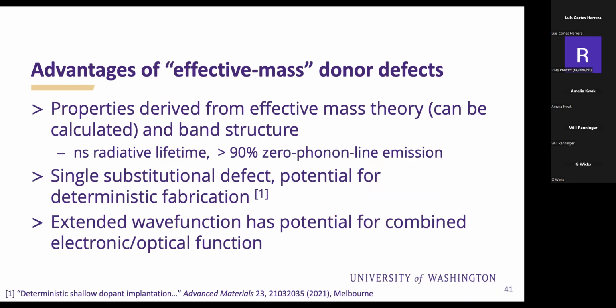Some advantages of effective mass donor defects are that the properties are derived from effective mass theory, which is a very well-established theory from band structure, or from Bloch's theorem, essentially. And then you have a single substitutional defect in this case, which gives you the potential for deterministic fabrication. Phosphorus in silicon gets 99.85% incorporation probability for putting in one phosphorus ion. That's pretty incredible in terms of yield. For a nitrogen vacancy center, you're jumping up and down if 10% of the nitrogens that you put in can yield an NV center, and that is a good yield for input.